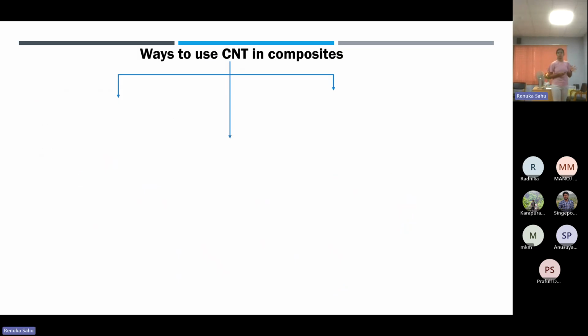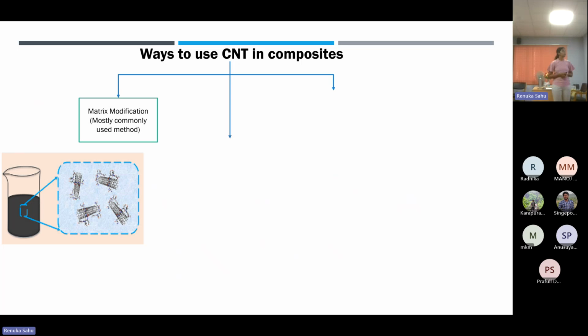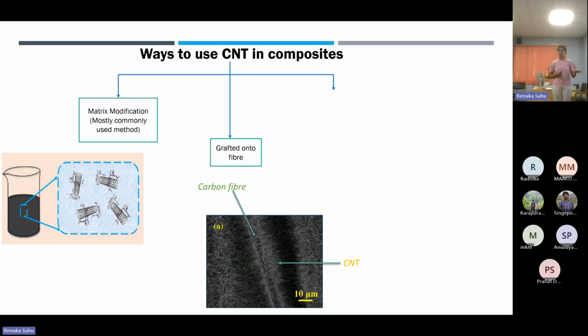And just to know, what are the ways to use CNTs in composites? The most commonly used method is the matrix modification method, wherein CNTs are just dispersed into a polymeric matrix, which is then cured and used as a composite structure. There is one more newer way, which is grafting onto fibers. This is a normal composite where you have carbon fiber reinforced into the matrix, but instead of a normal carbon fiber, we have carbon nanotubes grown all around the carbon fibers. This helps to increase the functionality of the carbon fiber, and it also helps to increase the transverse properties.